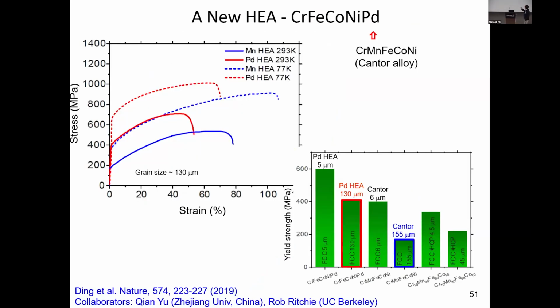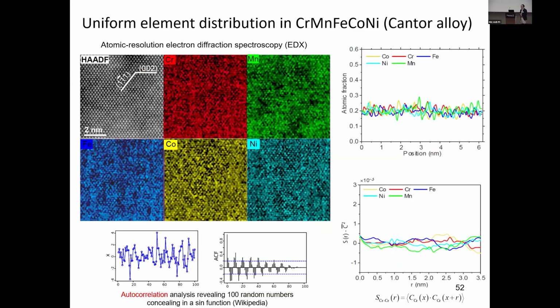In our case, we replace this Mn by the Pd. It's still a single-phase FCC solid solution, but you can see a very dramatic improvement of the yield strength. The blue curves represent the reference tensile stress-strain curve from the Cantor alloy at room temperature, solid line; dashed line is at liquid nitrogen temperature, while the red lines are our new high-entropy alloys. So at room temperature and at liquid nitrogen temperature, we have a significant increase of the strength, maintaining very good tensile ductility. So what's the difference here?